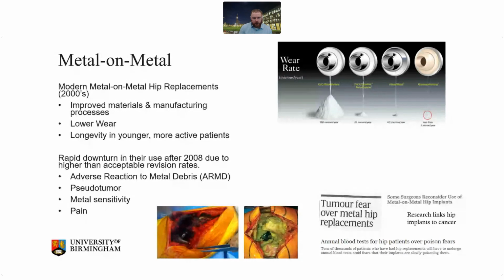But there was a rapid downturn in their use because there were essentially other failure mechanisms occurring there. So we started to see adverse reactions to metal debris, pseudotumors, metal sensitivity and pain, and then basically the vast majority of these devices have now been removed from market. Some had failure rates as high as, I think, approaching a third, 30% at 5 or 6 years. So polymer wear, or just benchmark wear rate from simulators, weren't a very good predictor for their success.